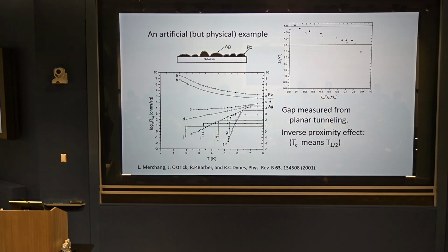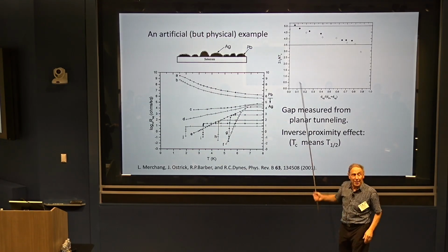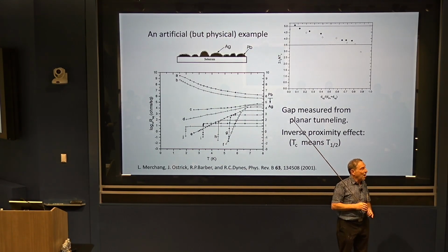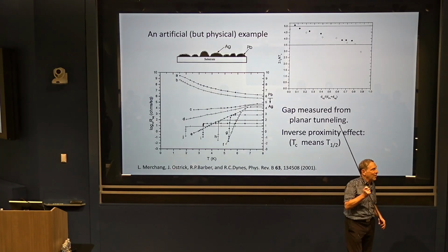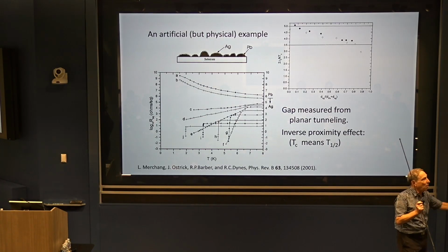So the Cooper limit is assuming the superconducting order parameter is uniform. Right. And so when you have very little silver, the superconducting order parameter is very non-uniform. It's much bigger in the lead grains and much smaller in the metallic regions between the grains. Once the silver gets to be enough, you go into this homogeneous superconducting phase.